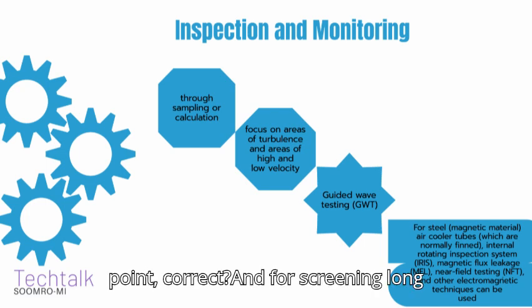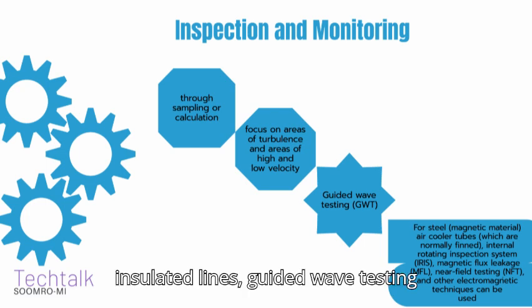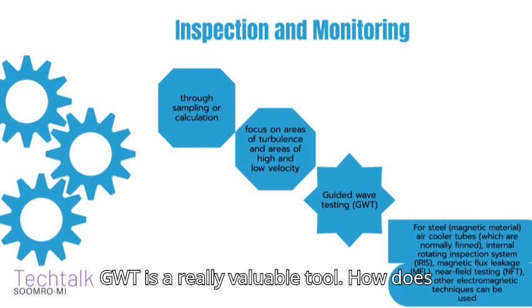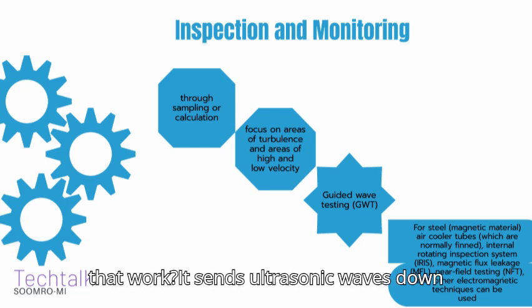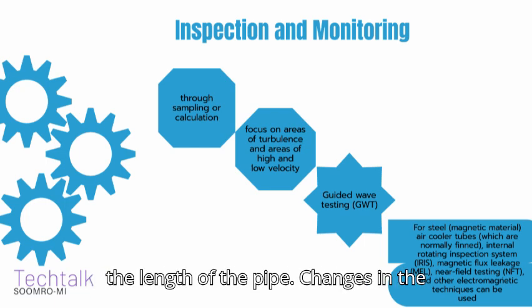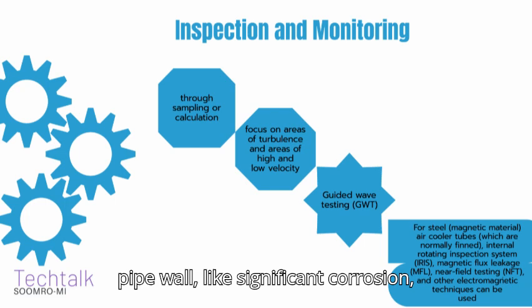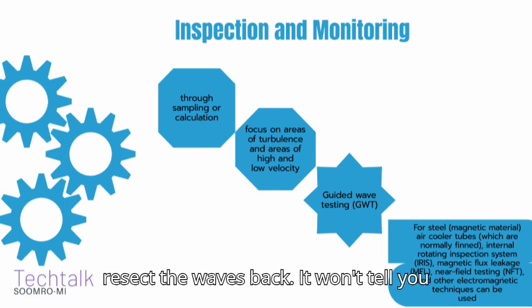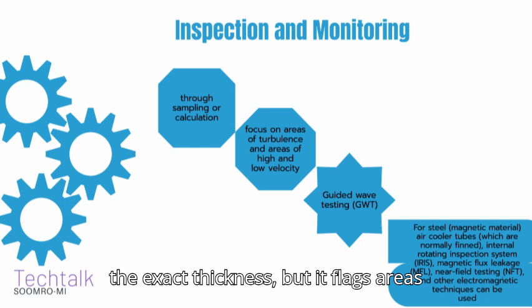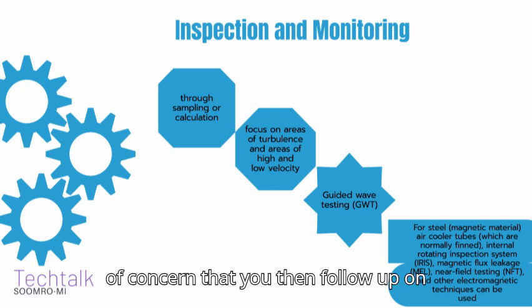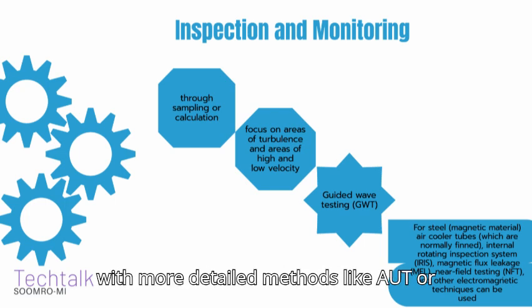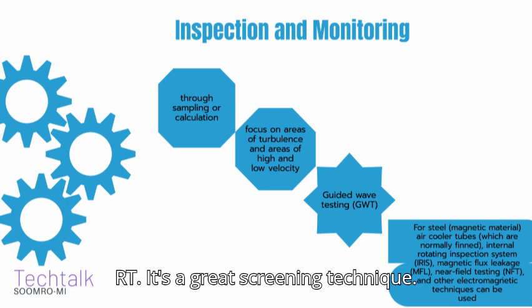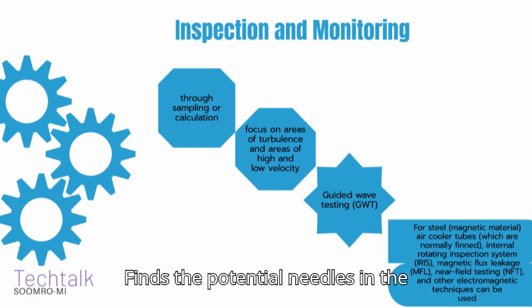And for screening long runs of piping quickly, especially insulated lines, guided wave testing, GWT, is a really valuable tool. How does that work? It sends ultrasonic waves down the length of the pipe. Changes in the pipe wall, like significant corrosion, reflect the waves back. It won't tell you the exact thickness, but it flags areas of concern that you then follow up on with more detailed methods like AUT or RT. It's a great screening technique. Finds the potential needles in the haystack.